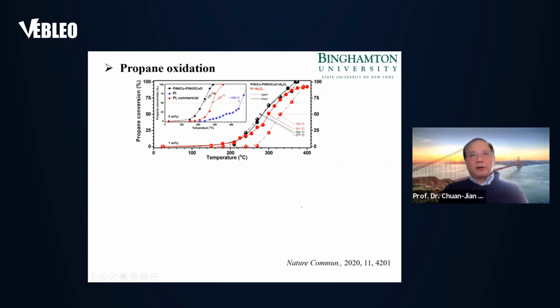Here in the top panel is a typical catalytic activity illustration. It illustrates the propane conversion as a function of temperature. You can see the nanoalloy with much less, 70% less platinum, shows catalytic activity higher than pure platinum. In the inset, you can also see that if you raise the loading, you can actually see even higher activity than the pure platinum.